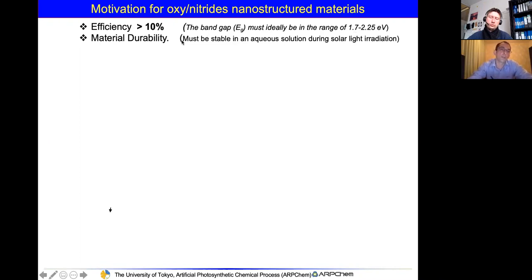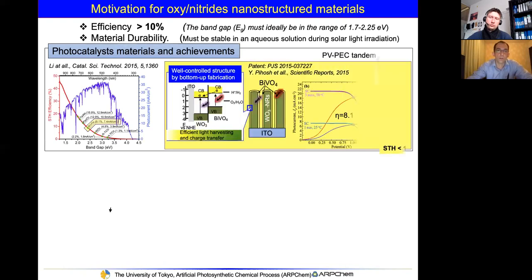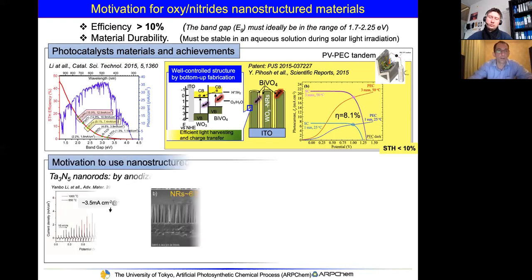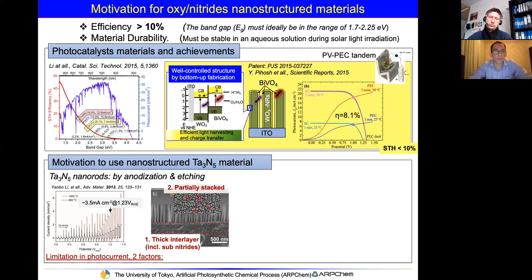And also about the material durability, it must be stable in the aqueous solution during the solar irradiation and the gas production. Okay, so I was motivated by my previous work, and I'm considering another material, which is tantalum nitride, Ta3N5. If you look here, the theoretical solar to hydrogen conversion efficiency of this material is almost 16%. So this is really an ideal material.